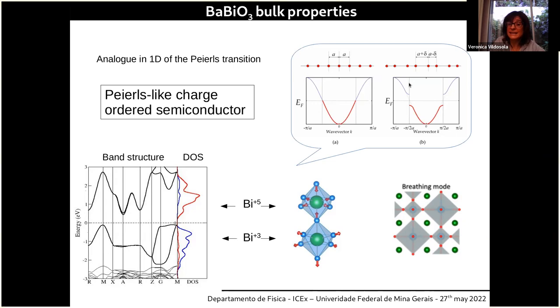due to the doubling of the cell, you have a downfolding mechanism, and there is this interaction with the crystal potential, you open a gap at the new symmetry points, and you end up with one electron per ion, but with a gap. And this is a metal-insulator transition due to the Peierls mechanism. And this is rather similar to what happens in bismuthate, because we don't have a dimerization, but we have to double the cell due to the breathing distortion, and that forces the oxygens to go closer to one bismuth and be further away from the other. And this induces this gap in the spectra.